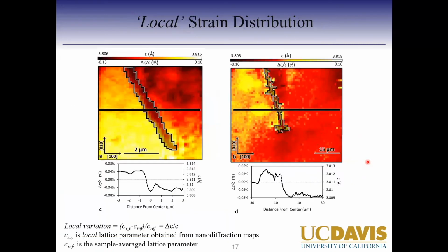Okay, so that's what we did here in this slide, where now we are plotting not just the intensity, but actually the strain in the sample. So this is the out of plane C lattice parameter, varying from 3.806 down to 3.815. And that's a variation of about 0.13 to 0.10%. So that's the advantage of this technique, we can map that out.